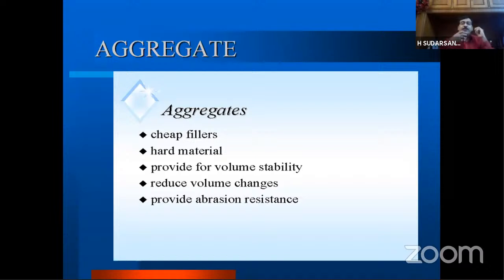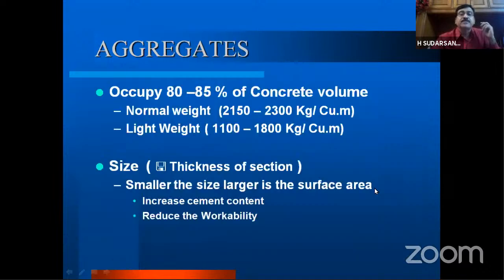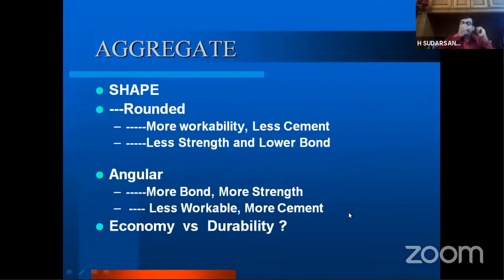Aggregates, you know, these are cheap fillers. They provide strength to the concrete. They reduce the volume changes and they provide abrasion resistance. They occupy about 80 to 85% of the concrete volume. And the size of the aggregate shall be smaller than the size of the member. The smaller the size of the aggregate, the larger is the surface area. So this increases the cement content and reduces the workability. So that is why it is better to use a proper sized aggregate.